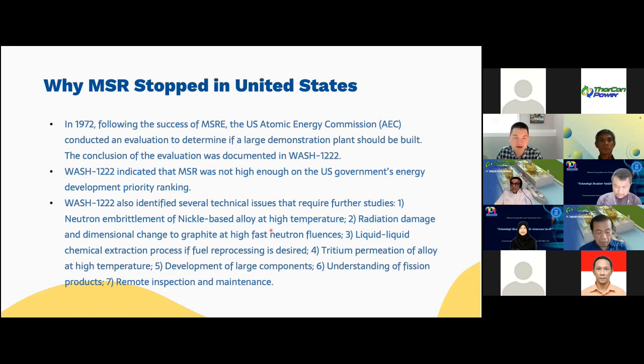The WASH 1222 also identified several technical issues that require further studies. The number one issue is the neutron embrittlement of nickel-based alloy at high temperatures. As you may know, MSRE is using a nickel-based alloy. Nowadays, we call it Hastelloy. There are several other versions of that. And it turns out that if the neutron fluence was too high, or the vessel was put into service for too long, there will be an embrittlement effect of the nickel-based alloy.